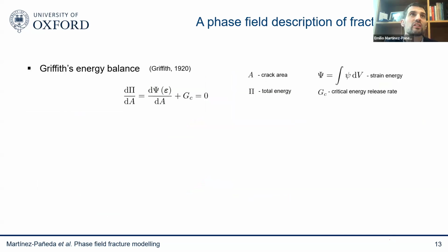And I think one of the beauties of this phase field method is that it provides a computational platform for Griffith's energy balance. So those of you familiar with fracture mechanics will remember that Griffith is the father of the discipline. He said, in order to be in agreement with thermodynamics, for a crack to grow, the energy stored in the solid has to be equal or larger than the energy required to create new surfaces, basically. What we call typically GC, the critical energy release rate, or the fracture energy, or the toughness.